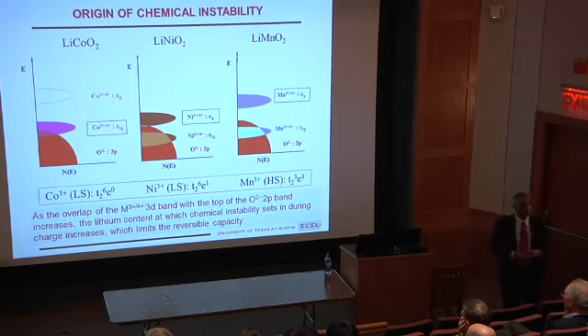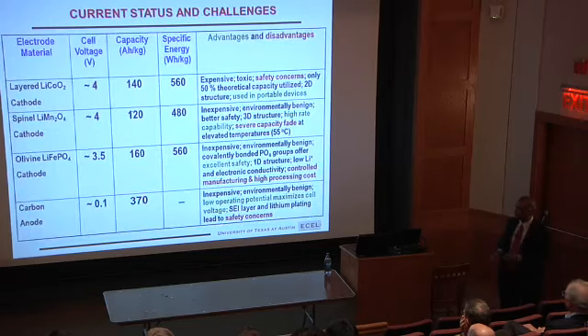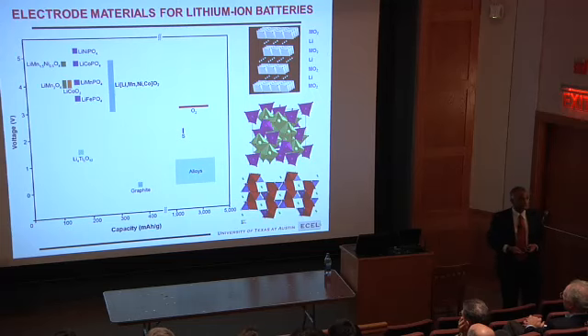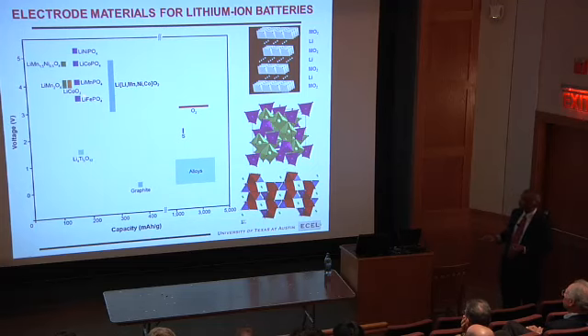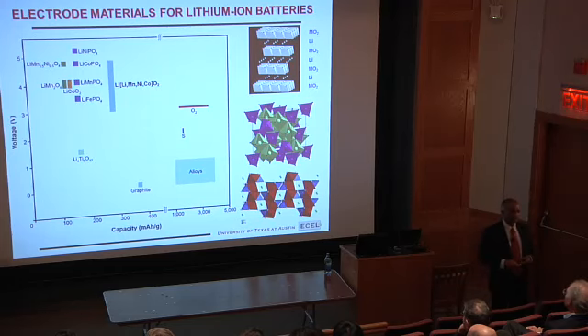In the case of iron, you deal with Fe2+, 3+ coupled as opposed to Fe3+, 4+ coupled. So iron is somewhere here, so there is a big charge transfer gap between the metal 3d level and the oxygen 2p. So it is a more localized system, less delocalized, less covalent. That means a lousy electronic conductor, this material. It is also a one-dimensional lithium-ion conductor. This is two-dimensional, this is three-dimensional, this is one-dimensional. So supposing there is a cross-substitution, a small amount of iron in the lithium site, that one-dimensional channel will be blocked. Lithium cannot move. So a lousy lithium-ion conductor.